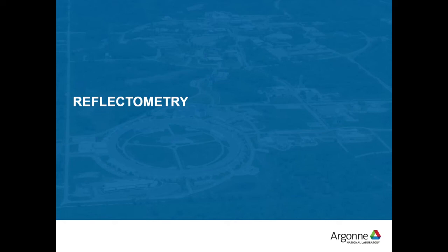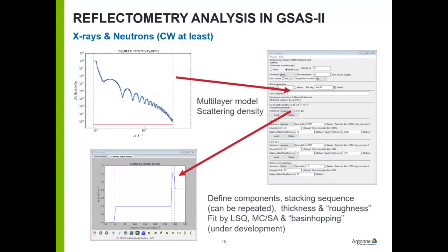Okay, you have a surface, say silicon, and you layer stuff on it, and you put another layer of stuff on it, and you want to ask the question: how thick are the layers? And do the layers intermix? And what happens at the upper surface? Is it smooth or is it rough or what have you? So you do that by bringing an incident beam at a very shallow angle and basically bounce it off the surface of the sample. And what you get then are basically